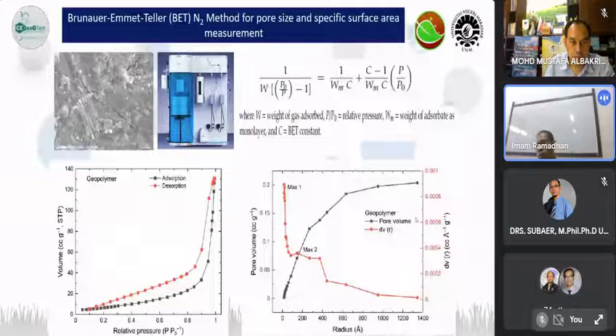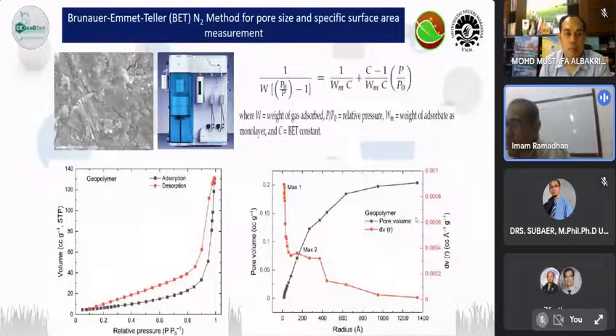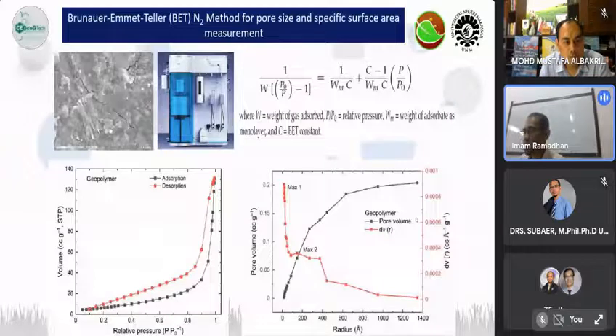method. You can use this BET method by using liquid nitrogen intrusion, or if it's not available, then you can also use mercury intrusion for your porosity measurement. But of course, using liquid nitrogen intrusion will give you more advanced information about the pore distribution, size, and surface area of your materials, especially if you direct your geopolymer to be a filter or a membrane. So this is compulsory for you to use these techniques to access the information on the pores of your geopolymer.